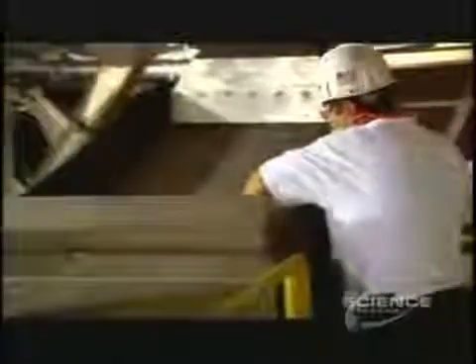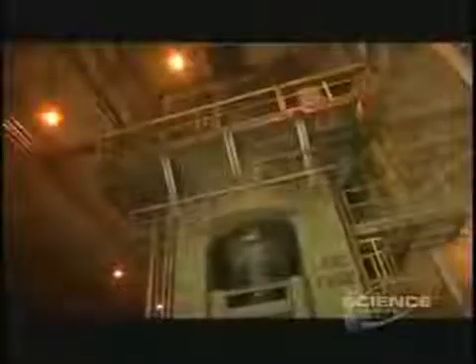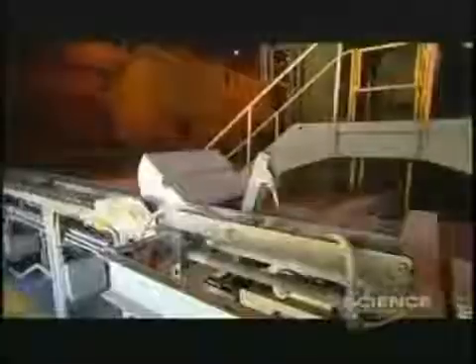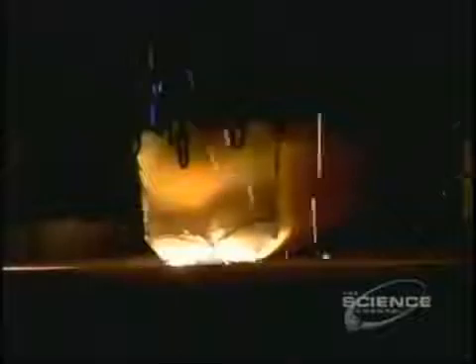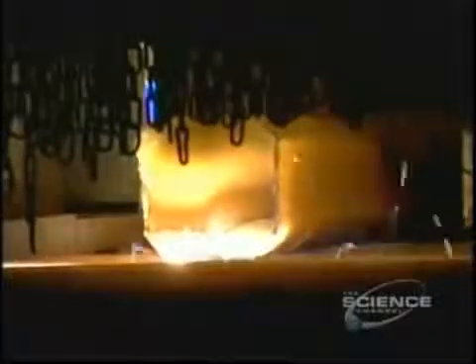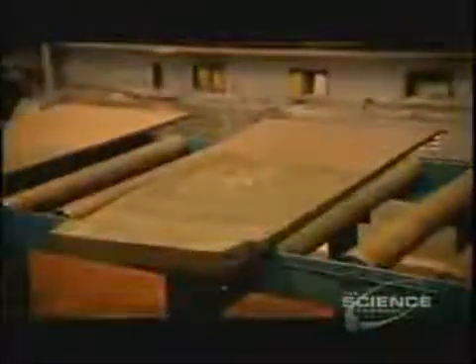This first involves taking 330 pounds of granules at a time and pouring them into a tube called a compacting press. A plunger is then forced down the tube, and using 7,000 tons of pressure, it squeezes all the metal granules into a half-round compact block. These compacts are then welded together into a round form and melted down in a vacuum to turn them into an ingot. Now all they need to do is turn these blocks into usable metal forms.